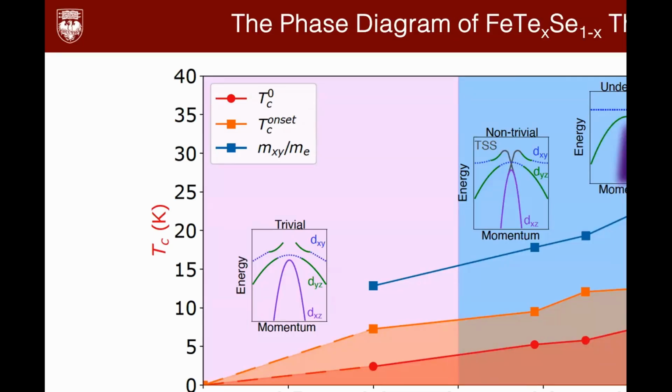So with that understanding, we really can redraw the phase diagram for the iron chalcogenide topological superconductors. The first topological transition around 0.7 was predicted, as you just change the tellurium to selenium ratio. But due to the strong correlation effect, the dxy contribution to the valence band makes this a correlation-driven topologically trivial phase again. So this highlights the important role of strong correlation. You really have to tune the correlation to the right amount, not too small, not too big, to lead to the right topological phase.